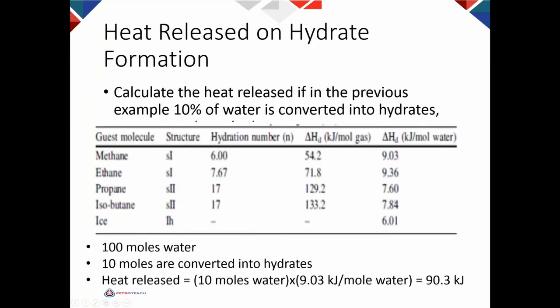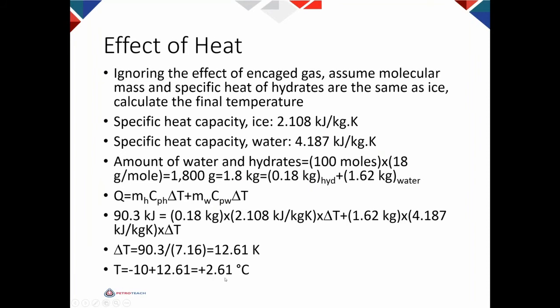This is the heat required for hydrate formation. Methane 9.03, ethane 9.36, propane, while ice is 6.01. So imagine you have methane hydrate. In the previous example, assume 10% of the water becomes hydrate. What would be the final temperature? So that's the calculation. You see that the temperature would be 2.61. That shows that the heat released during hydrate formation is much higher than the heat released during ice formation. You need to be aware of that.